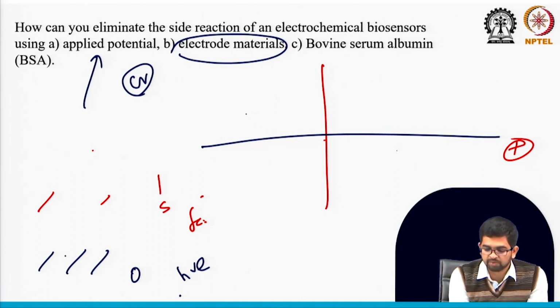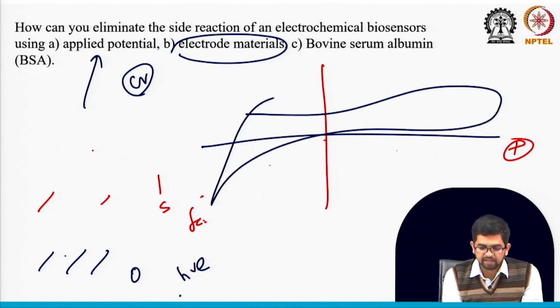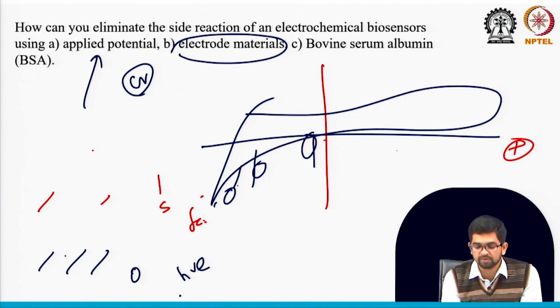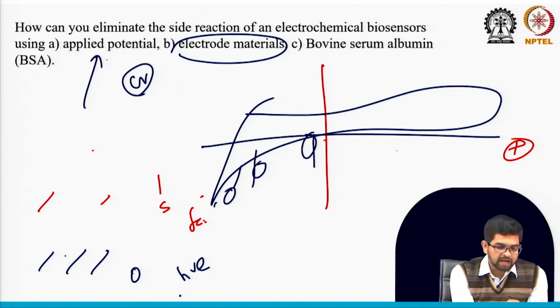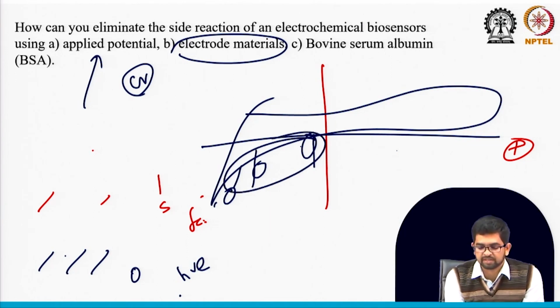First, measure a cyclic voltammogram in your chemical solution. As I said, your reduction starts from here, and you can see that here the reduction is actually increasing. So you can select your applied potential accordingly. Here oxygen reduction has actually started, which means the side reaction is large. Don't choose this potential, because you may get a high background current. Then select around this position.